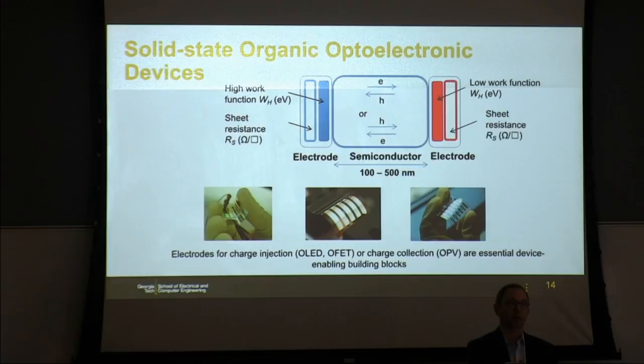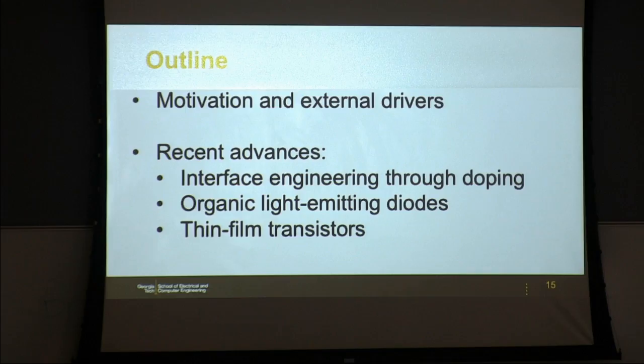And so for these electrodes, there are two properties that are really important. One is the work function, which is the energy it takes to basically remove an electron from that electrode, and then the conductivity or the sheet resistance, because you don't want to have high sheet resistance, otherwise you would have some losses, okay? And so these two properties can be combined.